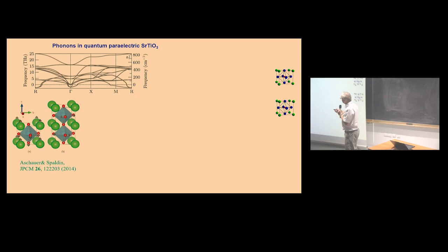So this expresses the soft phonon, because in infrared spectra we can see only phonons from the gamma point of the Brillouin zone. The rest of the phonons we cannot measure using infrared or Raman, and for that inelastic neutron scattering or inelastic X-ray scattering should be used.